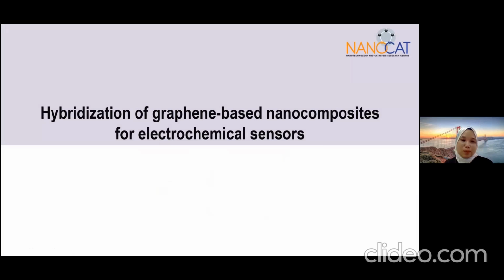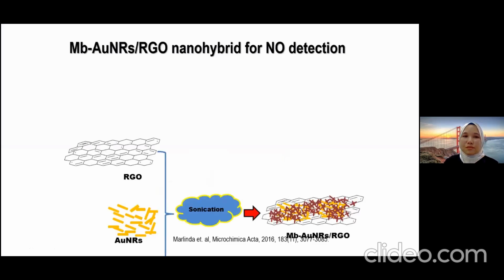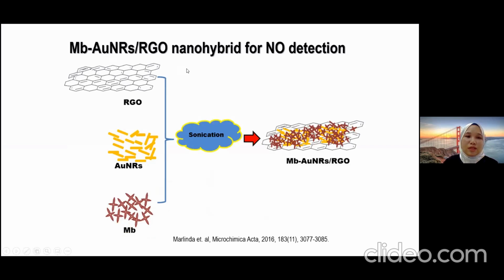Okay, let's see some examples of the hybridization of graphene-based nanocomposites for electrochemical sensors. This is one example, where we produce a myoglobin gold nanorod reduced graphene oxide nanohybrid for detection of nitric oxide. For the preparation process, reduced graphene oxide was combined with gold nanorods using the seed growth method, and then combined with the myoglobin by a simple sonication method. And finally, we obtain the nanohybrid, and this has been used for detection of nitric oxide.